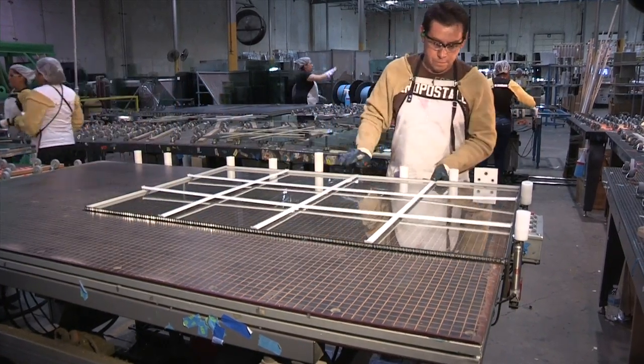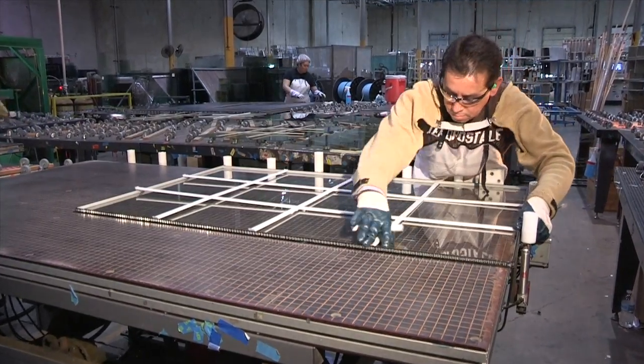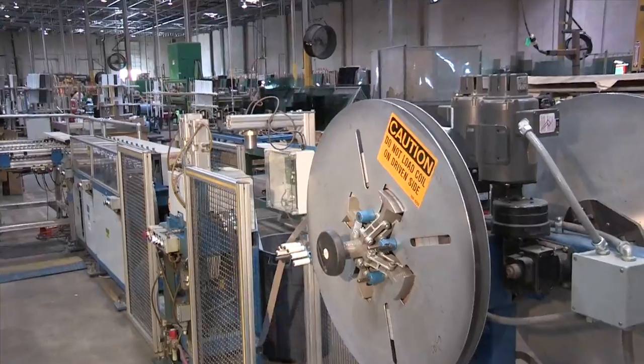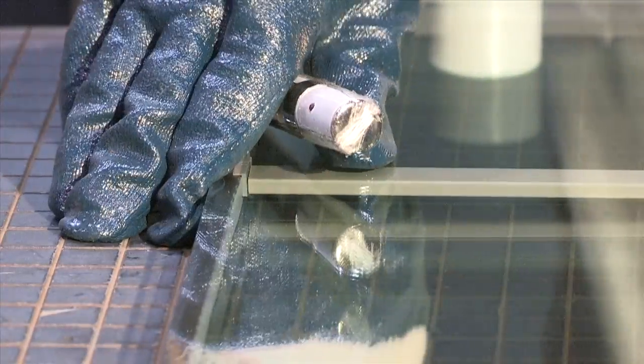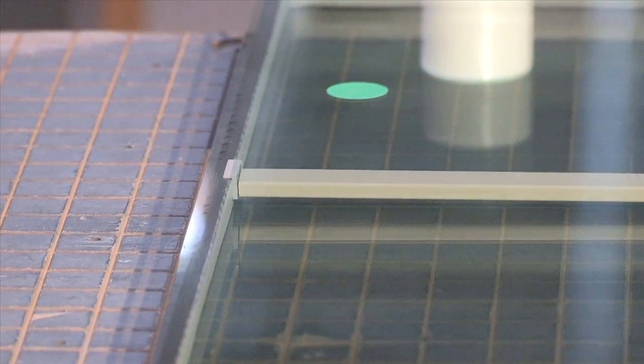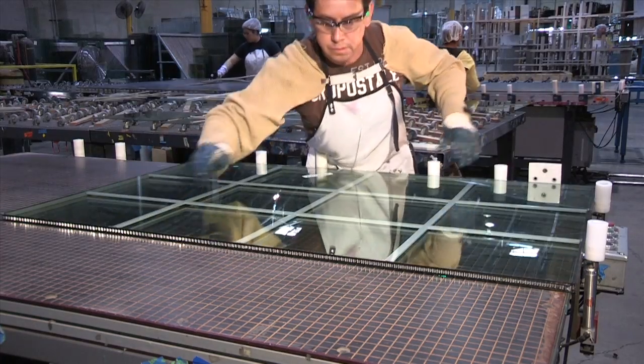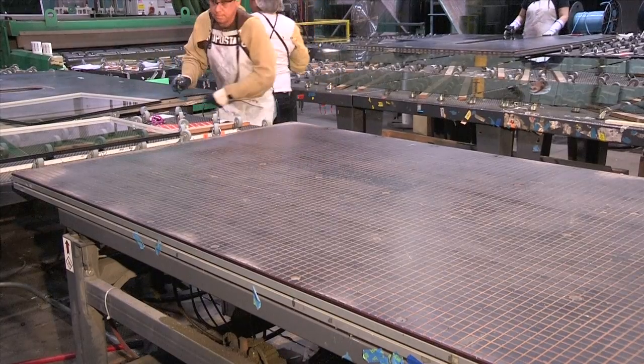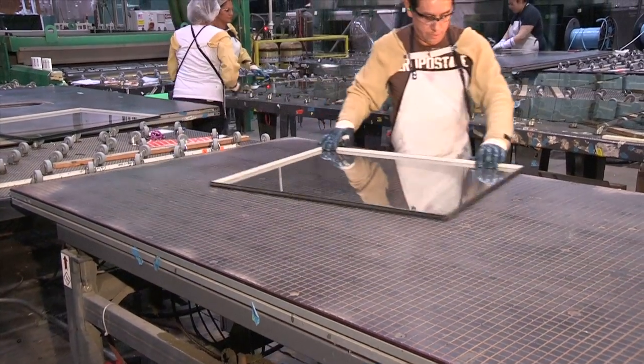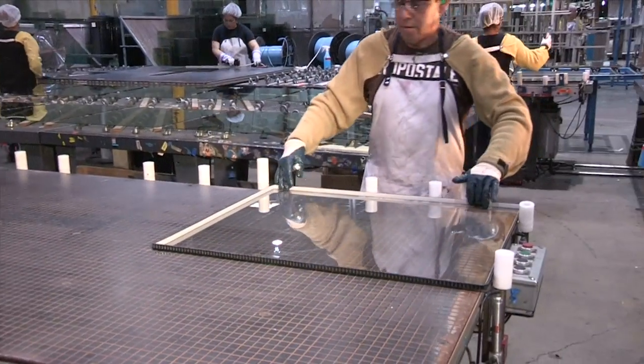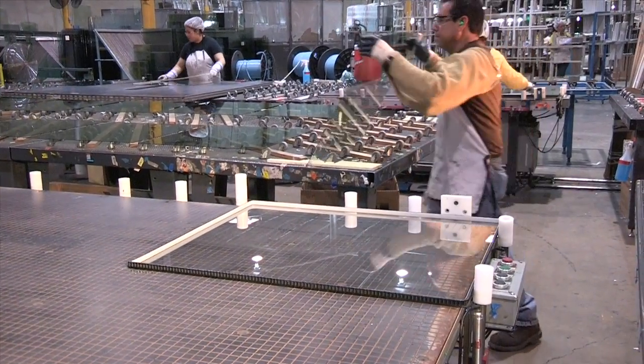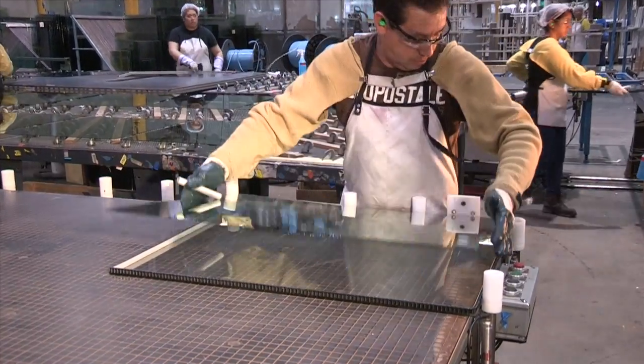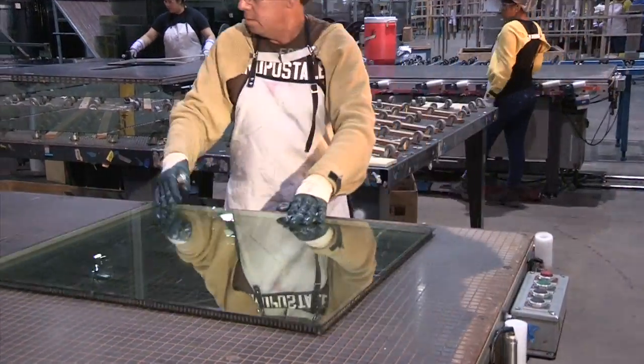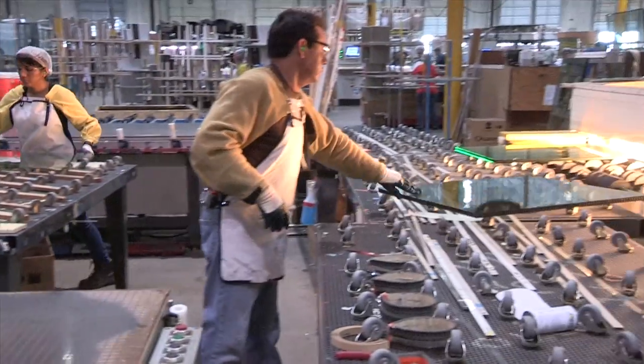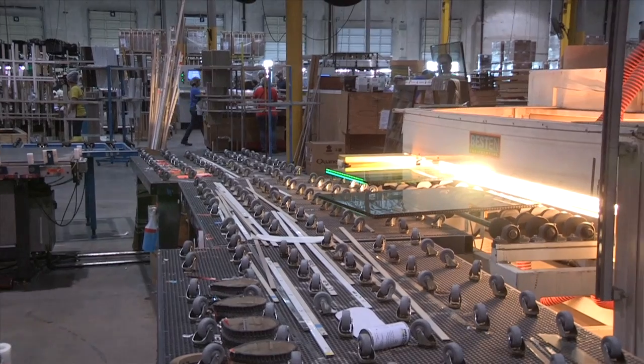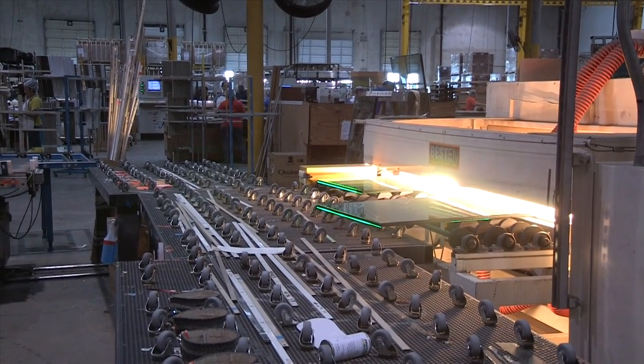Some windows feature decorative gridwork called muntin bars. These are created on this computer-automated machine to produce perfectly fitted internal pieces made of aluminum. Muntins are placed between the two panes of glass. This insulated glass unit will have insulated LowE glass with argon gas in between for added energy efficiency. One of the panes has a transparent metallic coating to reflect the heat back to its source, known in the industry as LowE. This helps reduce energy bills in the winter and the summer.